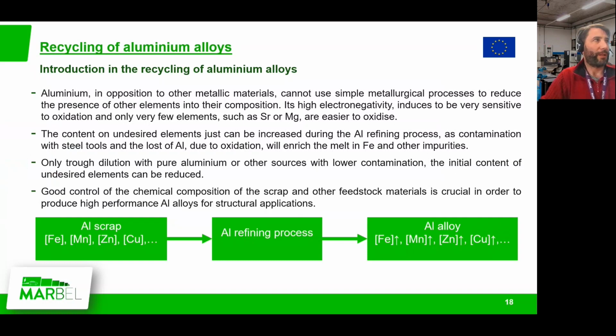So, regarding aluminum alloys, the recycling has differences over other metallic materials, because in aluminum it's not possible to reduce any element present in the melt. Whatever you put inside the furnace, you can refine, but it's going to be there at the end. So it's very important to control the chemical composition of the feedstock material, and not just control, but to have it as narrow as possible. The only exception is very few elements that are less electronegative than aluminum, such as strontium or magnesium, that are lost, and if you increase temperature and time, you can even try to reduce it further. But that's the only exception.